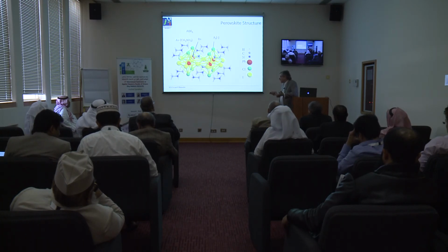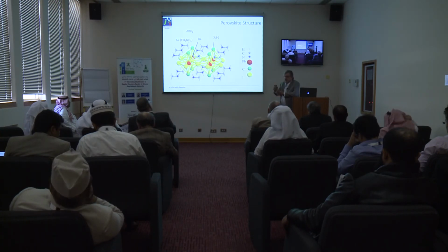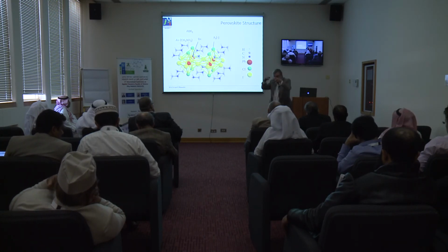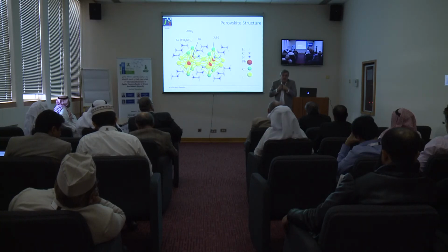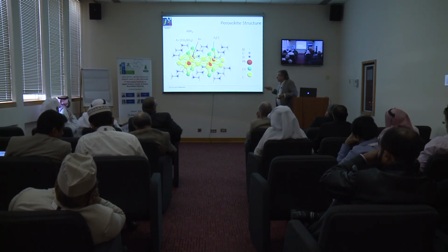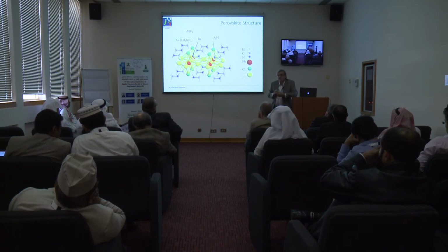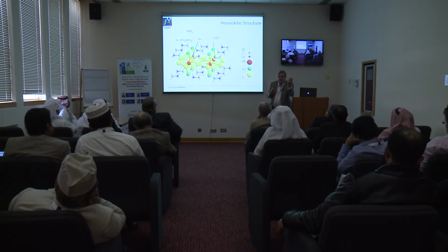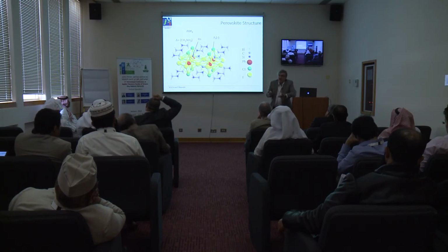So one is polarity. This is polar. This is polar, so this can rotate. Whenever something is polar, if you put a charge, the polarization will move around and remove the charge by a factor corresponding to epsilon, the dielectric constant. Okay. So one thing is that this is polar, and the whole structure is polar because it is a perovskite. In perovskites, you have polarity of the cage. You can move one ion a little bit with respect to the other ones, and this is another dipole.